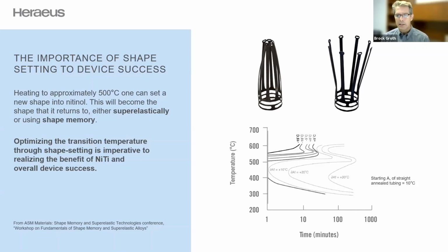This is a TTT curve, and so there's basically a curve that looks like delta AF plus 10 degrees C, delta AF plus 20 degrees C. Along that curve, you will move the transition temperature that amount by that heat treatment. So for example, if you do a heat treatment at 500 degrees C for about 10 minutes, you'll be between the plus 10 degrees C and the plus 20 degrees C curves, and you will move the transition temperature of the material by that amount.